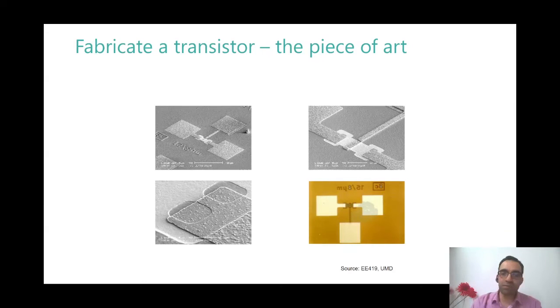Okay. And I think the one that we worked on was something like 0.5 micron technology or something like that. And you see this kind, you made a contact and you wanted to make a wire over it. But you see what has happened? Such a large part of the contact, there is no metal. So if there is no metal, it means silicon is contacted with metal through a lesser surface area. So the real resistance of this contact will be higher than the resistance that you had wanted it to be.